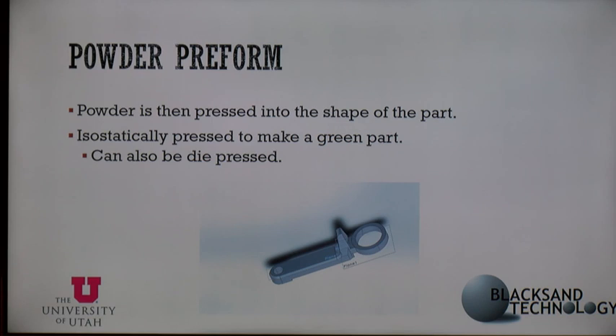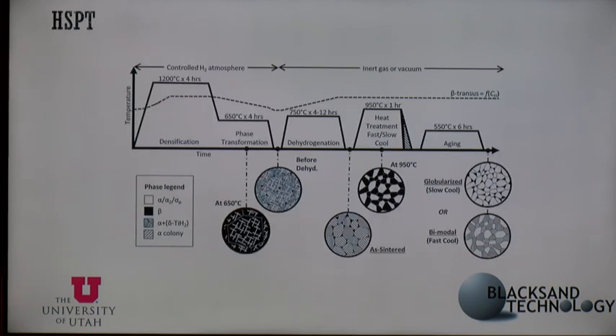Are there any questions on preforms? Okay. So this is our process. It's hydrogen sintering phase transformation. Basically, that's a very complicated way to say that we use hydrogen to sinter rather than it being under high vacuum. So you can see on the left, as we go left to right, we have that initial stage where we take it up to 1200 degrees C.